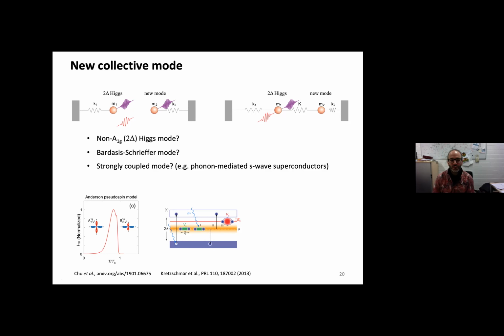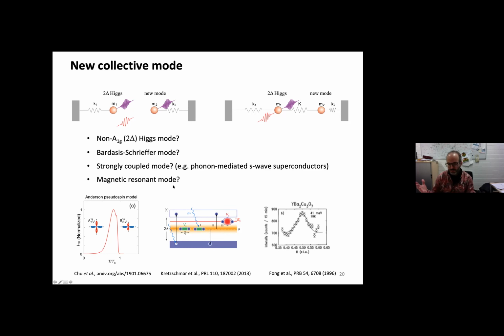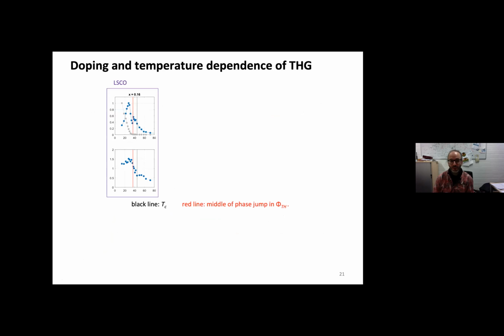Another possibility would be strong coupling to other modes. For example, in S-wave systems, one could directly think of phonon-mediated scenarios. However, in the cuprates, probably the magnetic resonance is one of the most famous things that we could think of, because also the energy of these modes is very, very close to the superconducting gap. And therefore, we also started to do a doping-dependent investigation of this. And this is now this optimally doped LSCO that we've seen before.